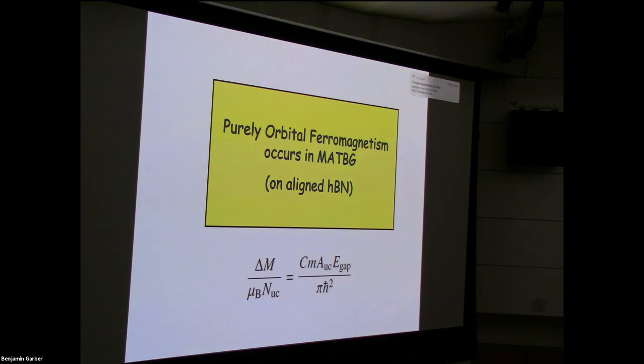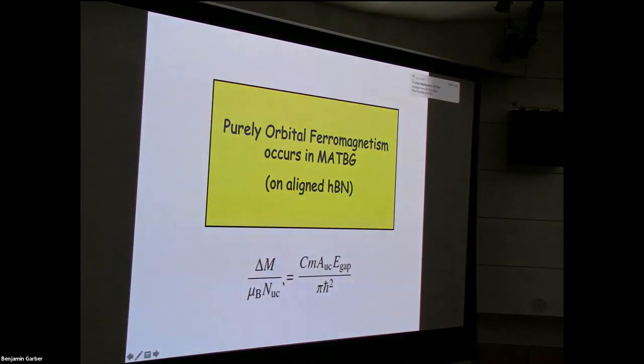I'll skip through maybe a couple of points quickly. The first one is just kind of an amusement. This quantum anomalous Hall state doesn't break translational symmetry, it breaks time reversal symmetry. We can call it a magnet, but it's an unusual magnet. And one thing that's unusual about it is that we know from the theory of the quantum Hall effect and from the correspondence between bulk and edge, and this actually goes back to observations about the quantum Hall effect first made by Bob Laughlin, that there are edge states.